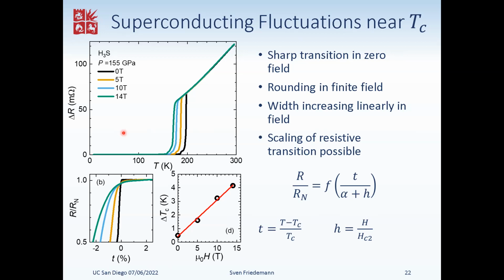There are, of course, other mechanisms that could give you a broadened transition, but many of them would also give you a broadening in zero field. Or it is about filamentary superconductivity, but that would give you a narrowing transition, or either completely suppresses your transition temperature very quickly if you've got a filament, or it gives you something which actually sharpens up as a function of field. Vortex, and then you see depending as a function of current.